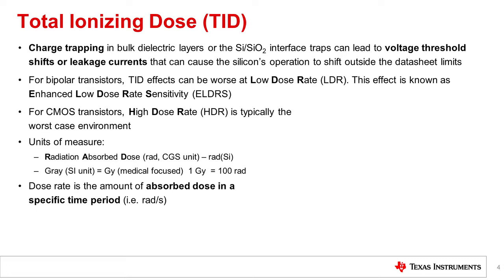Under longer exposure, this can cause a device to become non-functional. For bipolar transistors, TID effects can be worse at low dose rate, but for CMOS transistors, HDR is typically the worst-case environment.